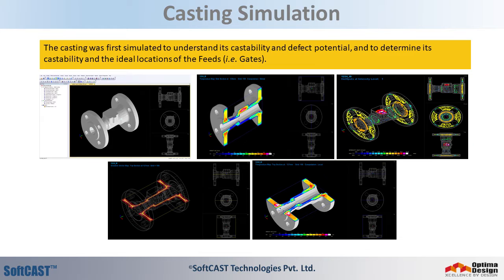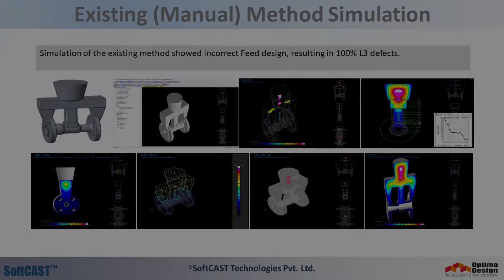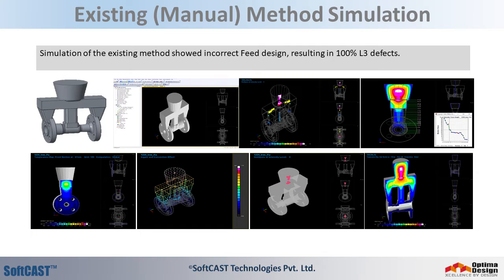The first step was to perform a casting simulation, the results of which, that is the hotspots, temperature maps and thermal traces, clearly showed the defect potential, the solidification zones, and the required locations of the gates. The existing method for this valve body casting did not assure quality at all, leading to 100% defectives. Simulation of the existing method showed incorrect feed design, which was the cause of the level 3 defects.